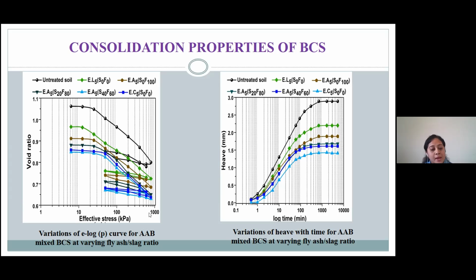The compressibility behavior of this AAB treated soil reduces significantly with an increase in the slag content. Adding slag to this soil-alkaline mixture enhances the rate of geopolymerization in the soil, which leads to a rapid dissolution of the precursor.